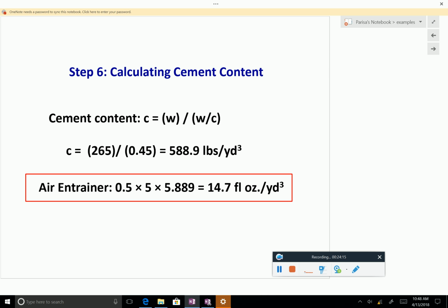It was 0.55 for strength, and then you also have to consider durability. And then you would get 0.45. And between the two, the conservative design is to go with the lower number. That's important. So you always consider both the strength and durability and choose the most conservative. Any other questions?